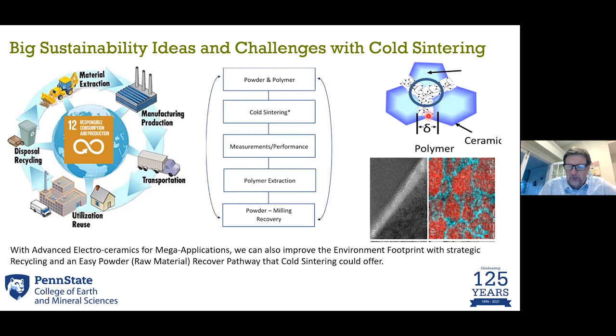So you can make a material which is maybe 95% ceramic, 2 to 5% of a polymer. You can cold sinter it. You can have the properties that you almost would see with a normal ceramic, but then you can do an extraction process to get rid of that polymer, either by heat or by a solvent extraction, and then recover really the all-important materials that may actually have compositions with very rare